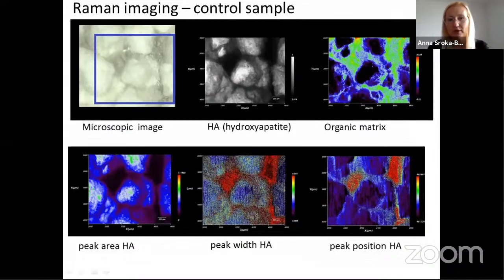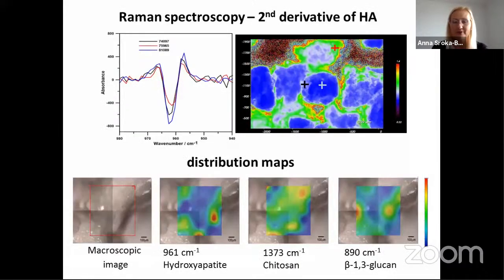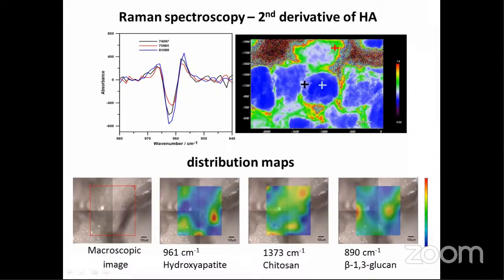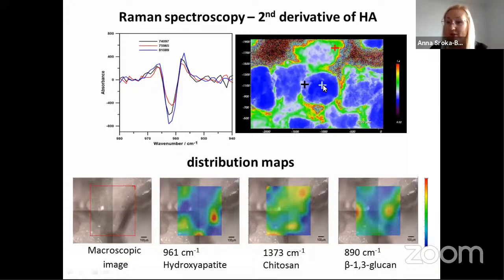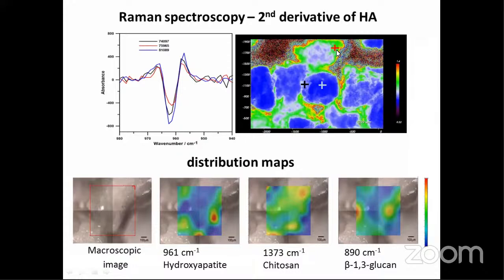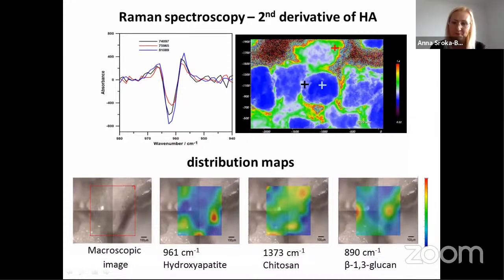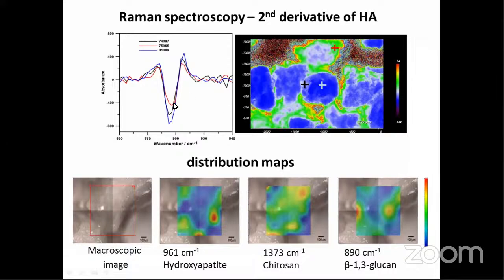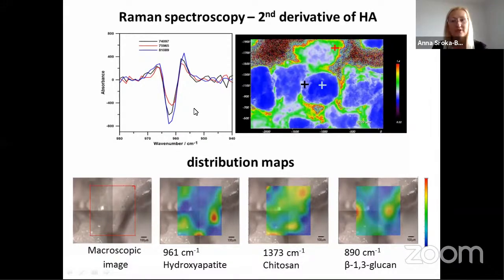To do that, we use the second derivative of the spectra to notice very small differences, for example, the shifting of the peak of the hydroxyapatite. From these points, we know that these are hydroxyapatite structures, and we look at how the spectrum looks in the middle of the granule and on the border. That part is from the polysaccharide matrix. So we want to notice if the 21-day incubation in the cell medium can influence the structure of the hydroxyapatite, and how much.